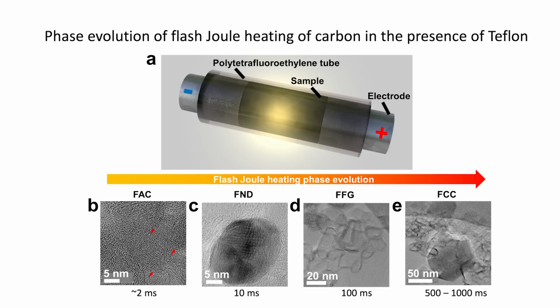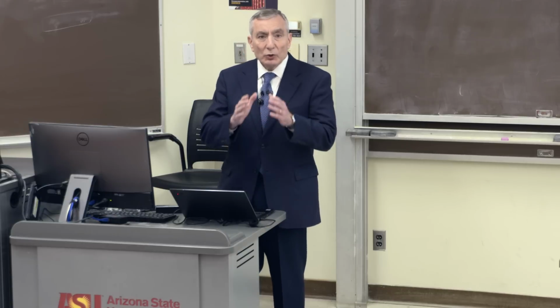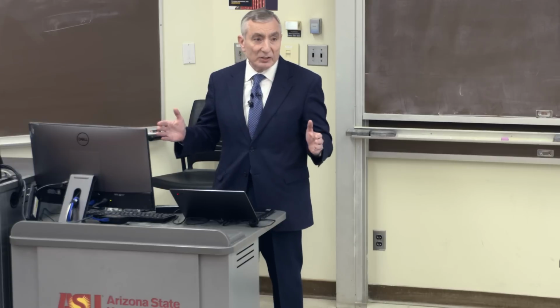If you continue heating to half a second or 1 second, you get these fluorinated concentric shells, these concentric carbons forming. So you can stop it at any point along this evolution because you're doing it with electronics. To stop anywhere at any millisecond time period over a 1 second time period is a very easy thing for electronics to do. It's just that our evolution time period is 1 second.